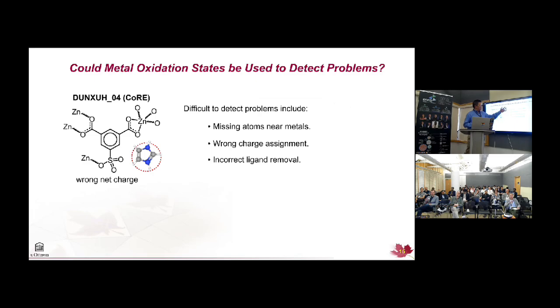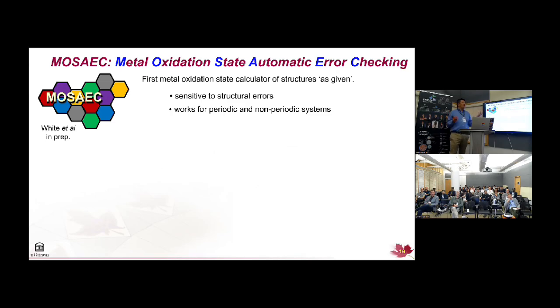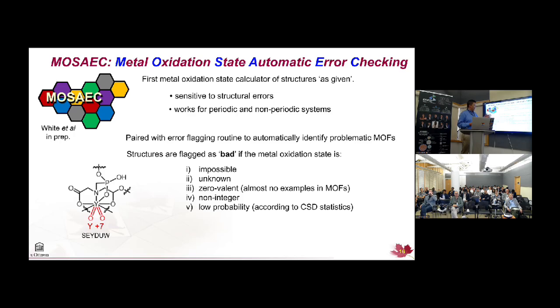So maybe it could be used to detect these problems that, as far as we know, there are no existing automated tools to address. We spent more than a year developing this code, called MOSAEC, which as far as we know is the first algorithm to calculate the metal oxidation states of metals for the structure as given. That's important. If you give it an erroneous structure, it will naively calculate the oxidation state of that structure. So it should be sensitive to errors, and it's fairly general, which I'll show you. We paired it with an error flagging routine so that if it computes an oxidation state and sees it's impossible or rare, there's probably a problem with the structure. Non-integer is also a problem.